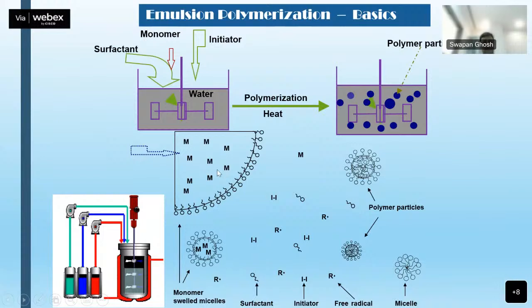The moment the monomer is added, it is an oil, a hydrophobic material, which will be stabilized by the surfactant again. But the monomer will actually move from the big droplet to these hydrophobic zones. The reason is that there is a high concentration here and a low concentration there, so diffusion takes place via the water. So after some time, we will have monomer-rich micelles. Now, the initiator will be there in the water. The moment we heat it, it forms radicals. These radicals will come and react with the monomer.